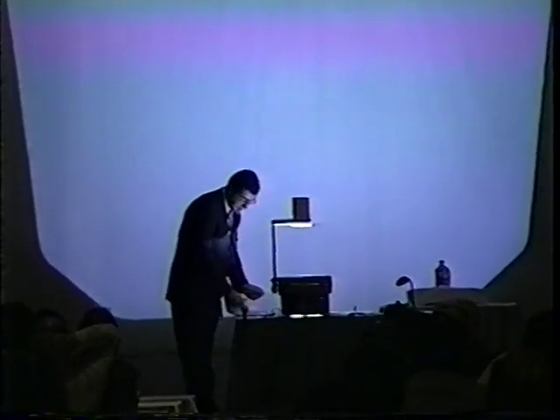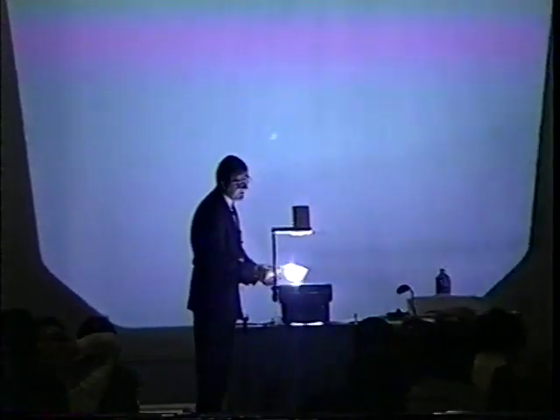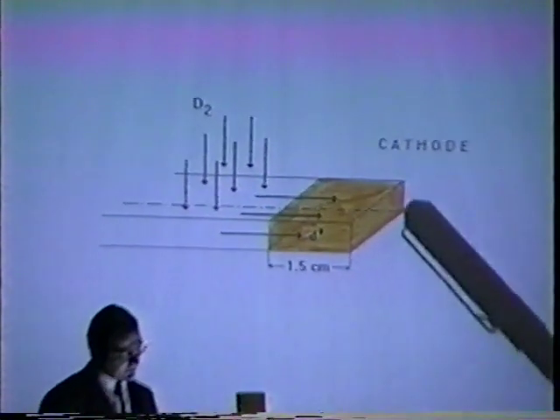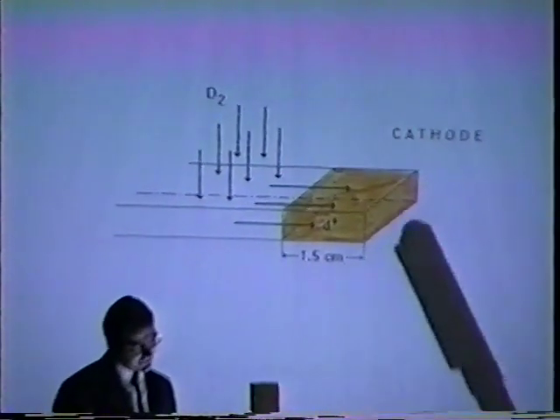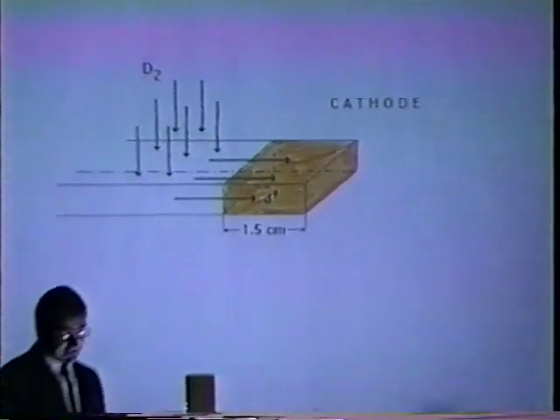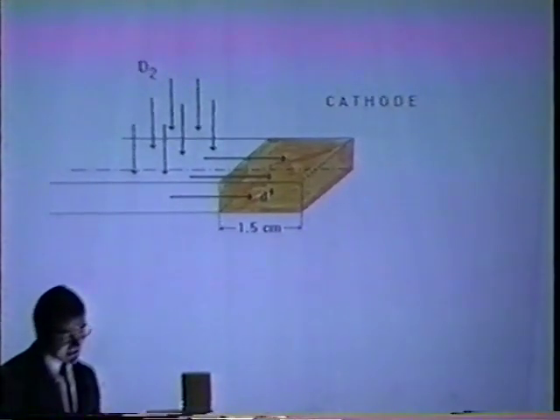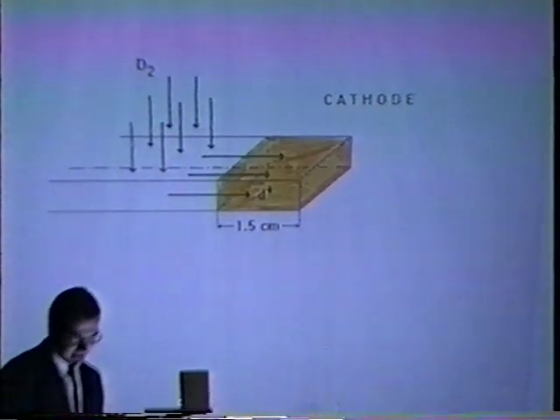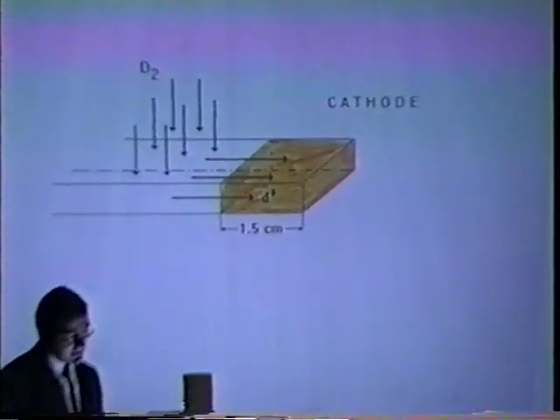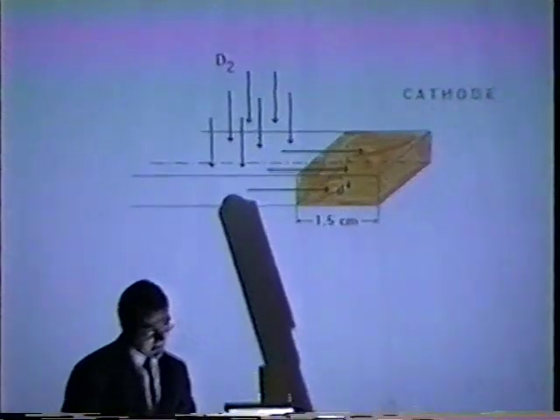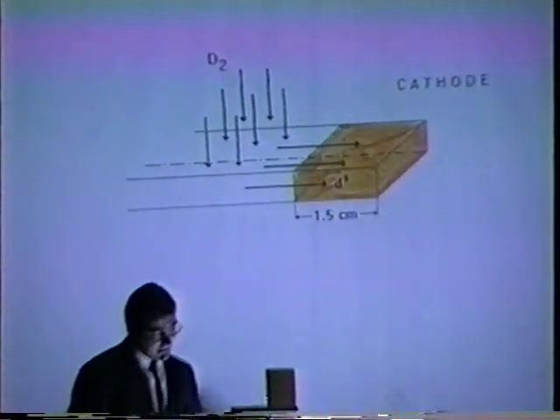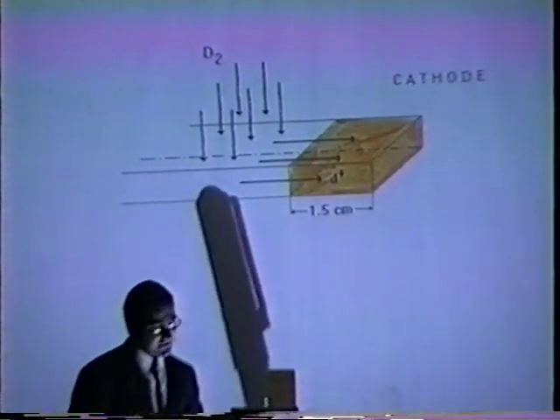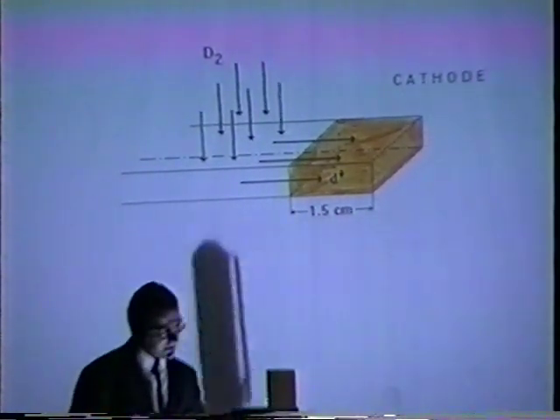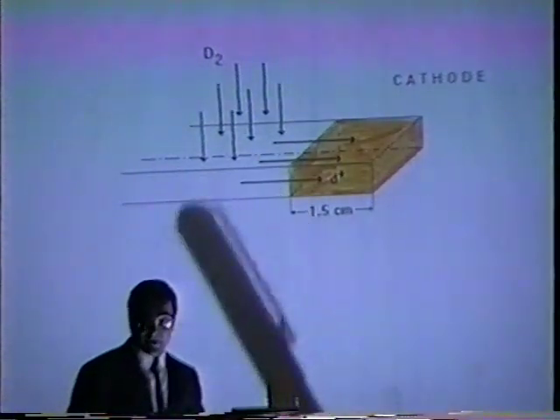The mechanism we like to use to enhance the loading ratio, what I call the Stern effect, may be summarized as follows. In this picture, only a region of the PD sheet is represented. The yellow part represents the gold coating at one end of the sheet. Normally, when the PD sample is located in the deuterium atmosphere, some gas penetrates the sample, following the so-called thermodynamical behavior of absorption of deuterium into palladium. When an electric field is applied to the sample, the ions already present in the metal are forced to migrate toward the cathode. This way, the concentration of deuterium is lowered in the central region that is not covered by anything. It's in direct contact with the deuterium atmosphere, thus favoring further loading from the gas atmosphere.